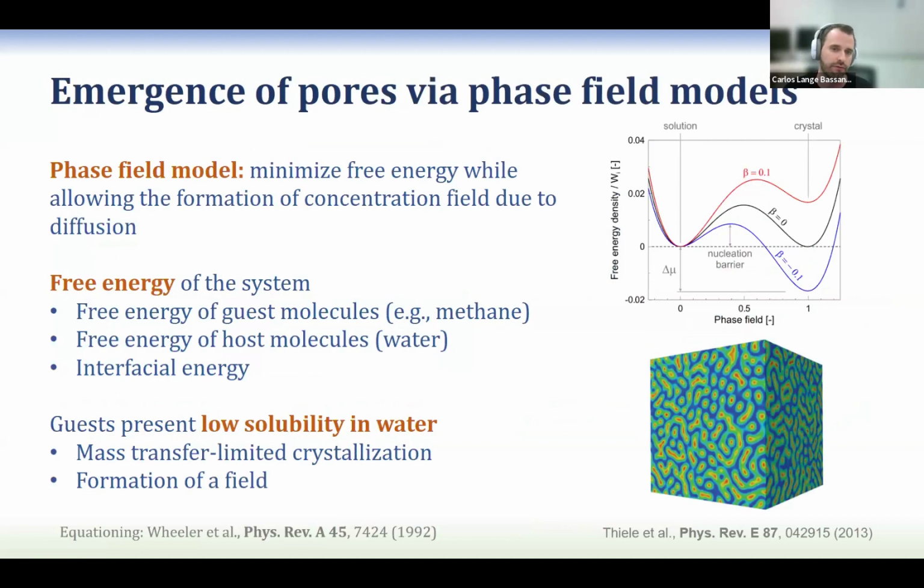One way of predicting this is through a phase field model, right? And a phase field model exactly couples the molecular scale with these mesoscales. So in the molecular scale, we have a free energy landscape, and we need to minimize the whole free energy of the system. For this we need molecular dynamics to predict exactly what the stiffness is, the nucleation barrier.